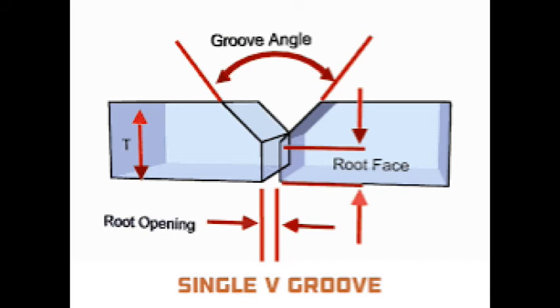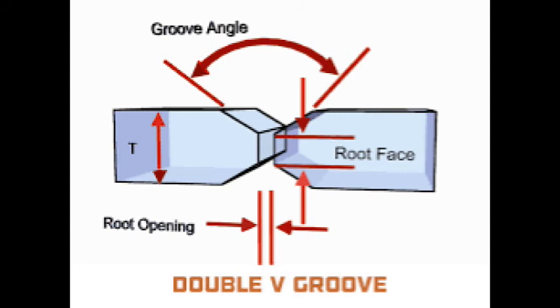In thick metals, and when welding can be performed from both sides of the workpiece, a double V-joint is used. When welding thicker metals, a double V-joint requires less filler material because there are two narrower V-joints compared to a wider single V-joint. Also, the double V-joint helps compensate for warping forces. With a single V-joint, stress tends to warp the piece in one direction when the V-joint is filled, but with a double V-joint, there are welds on both sides of the material, having opposing stresses, straightening the material.